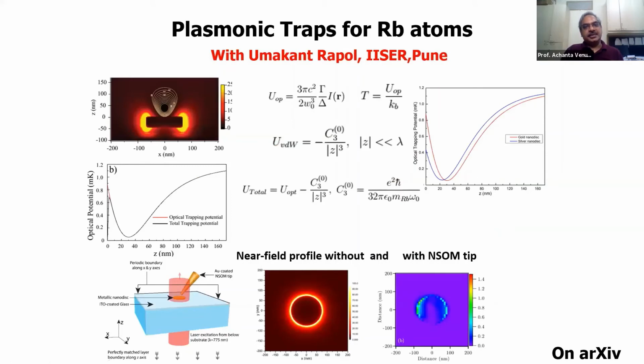These plasmonic structures are also interesting for optical traps, for example on-chip optical traps. We designed these metallic discs and studied silver and gold discs, and showed that gold has a much deeper potential profile for trapping these atoms. We can design the structure starting from which atom and which wavelength we need to trap. We measured these near-field profiles and showed that this potential profile actually exists on top of these metallic discs.